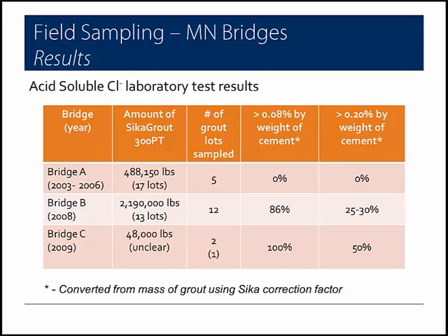Bridge B, built in 2008, has a little over 2 million pounds of SikaGrout 300PT and 13 distinct grout lots. 12 of those grout lots were sampled, and the vast majority exceeded the PTI specified limit of 0.08% by weight of cement, with approximately 1/4 to 30% exceeding 0.2% by weight of cement, or 2.5 times the PTI specified limit.